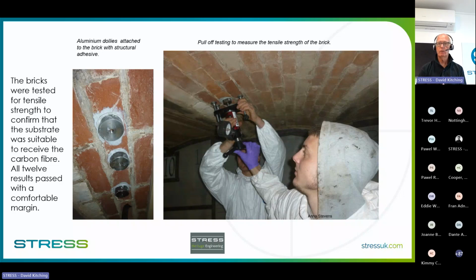And of course, to get the bond that you need between the carbon fiber and the brickwork, you have to test it. You've got to know what's going to happen, because let's say you've got something as stiff and as load bearing as carbon fiber, but the surface of that brickwork is friable. It'll just pull off. It'll never transmit the load. So you need to get a really good idea of what that bond strength is at the surface. And what you do is you take these 50mm diameter dollies, which are about 2,000 square millimeters, and you bond them to the brickwork, and then allow that adhesive to go off, and then pull them off normal to the surface and see what sort of bond strength you've got.